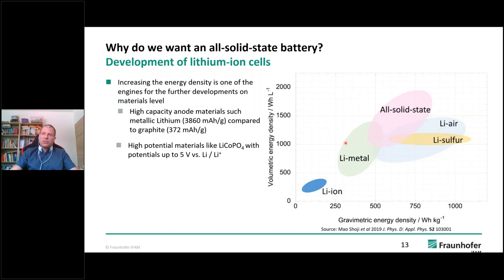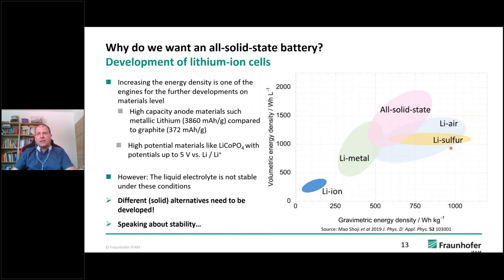And we can see that when we achieve lithium metal batteries like this, we even increase it, going over 1000 watt hours per liter and achieving maybe 500 watt hours per kilogram. Going to all solid state batteries, we can even increase this. And I will go into why this is. We have different systems, which I will not go into detail on, like lithium sulfur. So this is the prospective energy density. The problem is that under these circumstances,